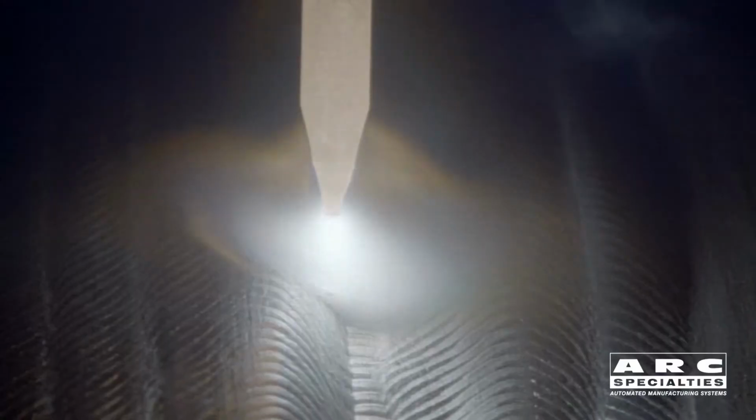The reason we decided to showcase this weld is because it's a bit unique. The base metal is high-strength, low-alloy chromoly steel that's heat-treated, but the filler wire is actually a nickel-based alloy. What we're doing here is qualifying the weld wire to base metal strength levels to allow the overlay to be used as part of the strength calculation on this valve. After the welding and post-weld heat treatment, this plate will go to the lab for destructive testing.